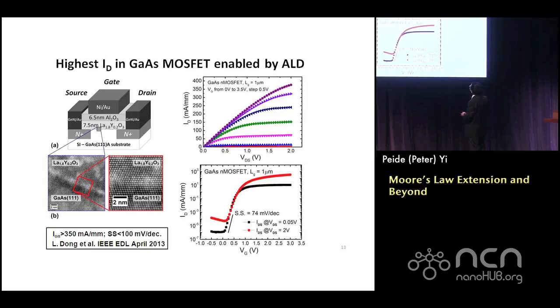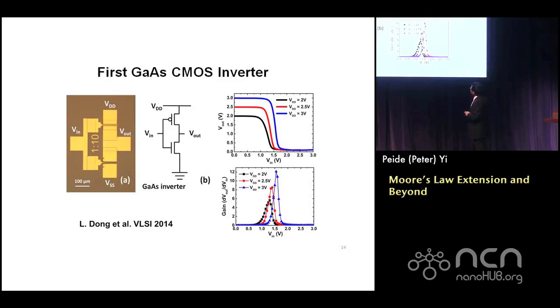So you can realize a very large inversion current, probably 1,000 or even 10,000 times higher than anybody else's. You really break the fundamental so-called Fermi level pinning issue on the gallium arsenide. And because the defect density is so low, you can also turn off the device very effectively. We usually call this the subthreshold slope. So you can not only turn it on, you can turn it off, and you can do more. You can transport not only with the electron but also with the hole. A hole is basically a positive charge. The electron is a negative charge.